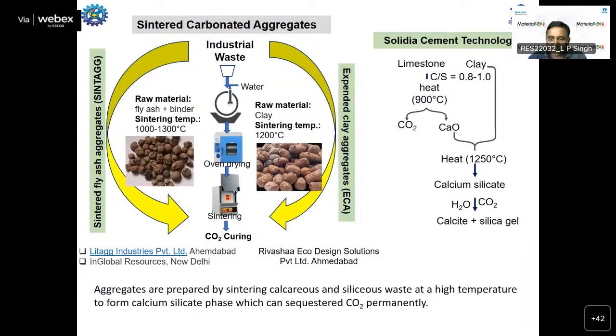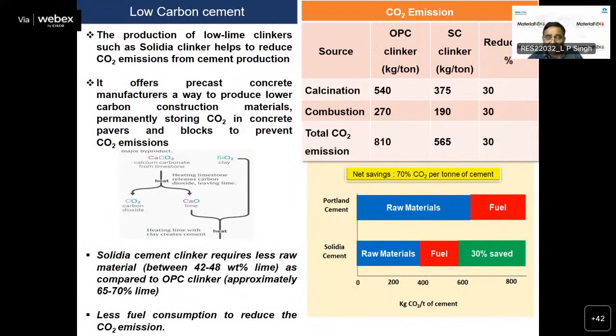There are two ways of making aggregates. One is sintered fly ash aggregate. Second is expanded clay lightweight aggregate. These are the two established technologies. What CBRI is trying to do, there is a recent technology, Solidia cement. Normally cement is manufactured at a temperature of around 1500 or 1550 degrees centigrade, but Solidia cement produces carbonatable phases at 1200 degrees centigrade. So we are fusing both the technologies and we are sequestering more than 20% CO2 into these artificial aggregates. Apart from that, we are also working on low carbon cements,